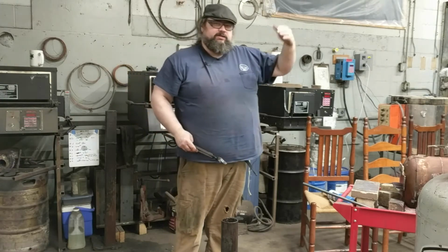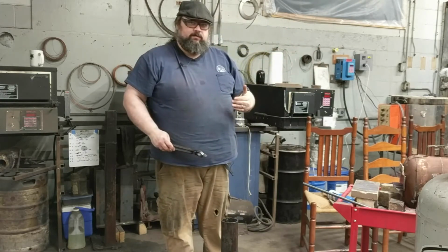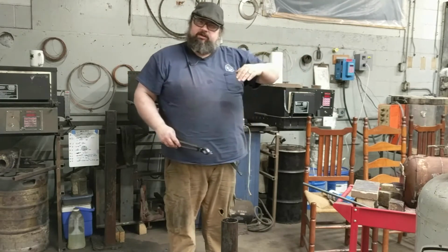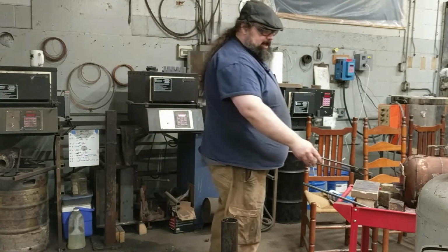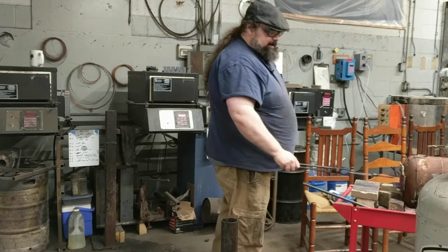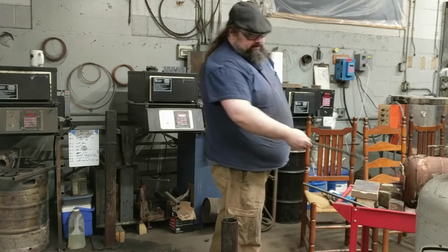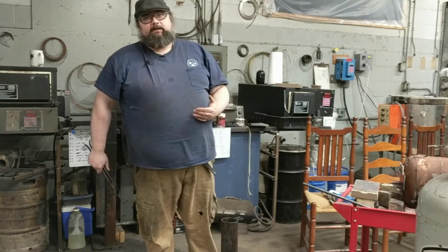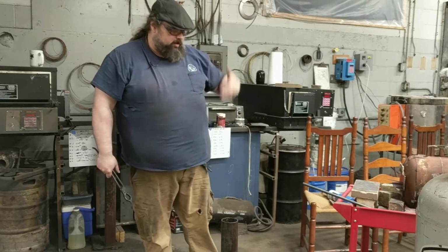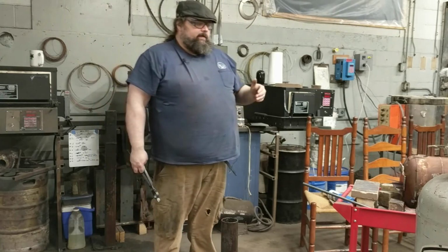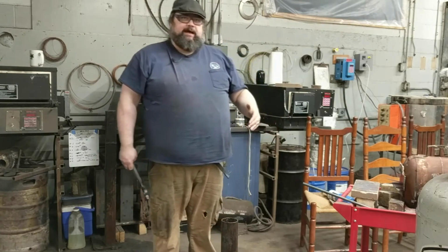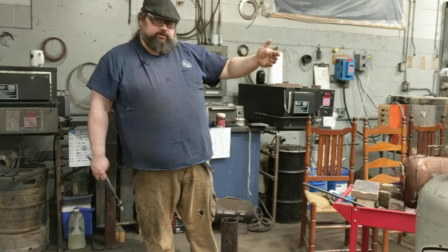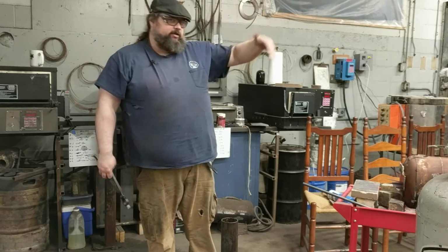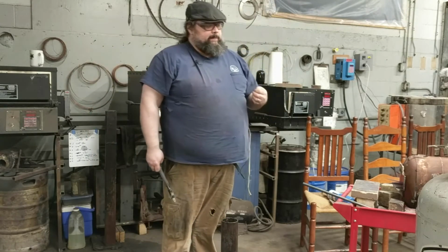And that quenching starts the moment you take it out of the fire. You have a certain amount of time to get below a certain temperature to make it happen. So like right now, if I pull this out, I'm quenching it, even though it's not going to go into the oil. I want to let it cool all the way to black. If I have exceeded that temperature, then I'll reset the grain and it'll start all over and it won't damage anything.